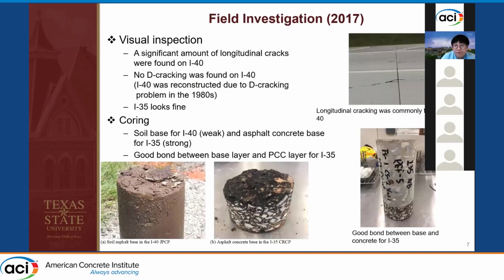So in the summer of 2017, Dr. Mukhopadhyay, Dr. Zollinger, and we went to Oklahoma City for the pavement inspections. We did a visual inspection. We found there was a significant amount of longitudinal cracks on I-40, which is the JPCP section. We did not find any D-cracking issues. Remember, I-40 was reconstructed due to D-cracking issue in the 1980s. And for the CRCP I-35, the pavement looked very good.